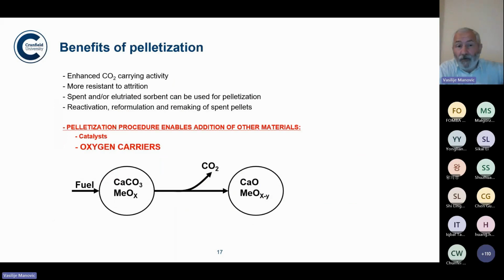So at that stage of development of materials, we were thinking, okay, now we have enhanced activity, many good things that I mentioned already. But we were thinking, why not, since we are making new material from powder, add even something else in that material. And we considered catalysts or even oxygen carriers. I will not be talking much about catalysts now, but if you have a process where you need something to capture CO2, a sorbent for CO2, but also need a catalyst in the system, you can put them together in the particle, to have a composite particle with sorbent and catalyst. But more interesting was adding oxygen carriers.